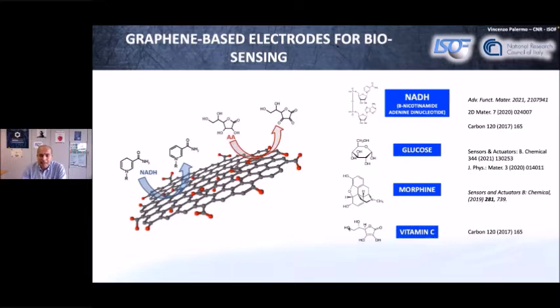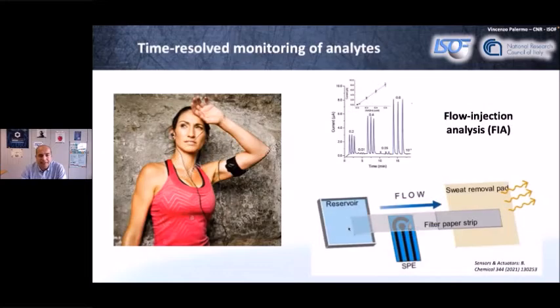So these were all, let's say, lab works, but of course for real sensors in a real environment the situation is much more complex, because you don't just dip your electrode in a solution where there is only your material and the concentration is stable. For example, if you want a sensor that detects your status when you run, of course your status and the concentration of analytes in your sweat on your skin will change. So for all these sensors, you should test if they are reproducible, giving the same measurements over time, and if they have some memory effect. They should measure a high concentration, then a low, then a high, and should not just go linear. That's why we even had to set up a special process to simulate this dynamic flow of sweat in a sensor.